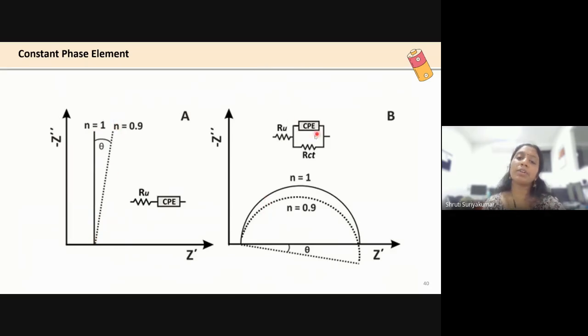And when it comes to an RC parallel combination, it's not going to be a semicircle here, but actually a semicircle that is tilted, and the tilt angle is given by theta. This tilt angle tells you how suppressed your semicircle is, and that is mathematically associated with the constant phase element parameter. So anytime we fit, if you are getting an ideal semicircle, use a capacitor element for fitting. And if you are getting a suppressed semicircle, you can better use a constant phase element, and that is going to be more or less realistic.